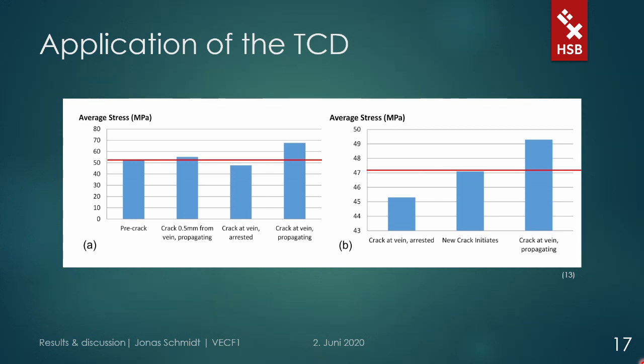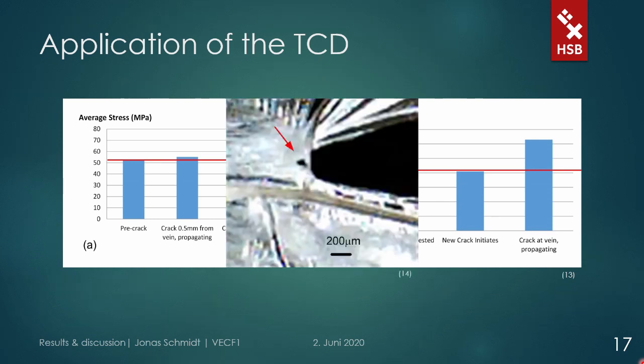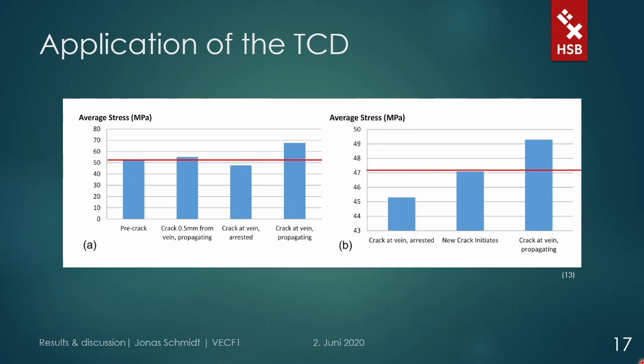On the right side we see part of the analysis of a second sample. Here the crack propagated slightly differently through the vein — a new crack initiated behind the vein before the actual vein failed, which was afterwards connected to the initially growing crack again. In this case the TCD applies again. When the new crack initiated, the average stress was interestingly slightly below the ultimate tensile strength, while the value was then again higher as the crack started to propagate again, but now with a considerably lower prediction error of only about 2 MPa above the UTS. This point of higher stress matches roughly with the position of the new crack initiation, suggesting it might give us a fracture criterion.